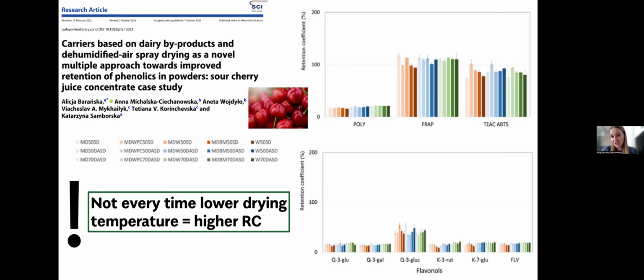With the retention coefficient, something that has to be studied more is definitely how the dehumidified air influences this parameter. So in the case study on sour cherry juice concentrate, where different dairy byproducts were used as carriers, we used chromatography to verify the bioactive compounds content in the powder in comparison with the sour cherry juice concentrate. And what we can say right now is that not every time lower drying temperature will mean higher retention coefficient,